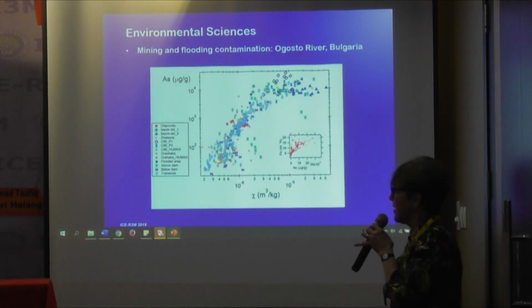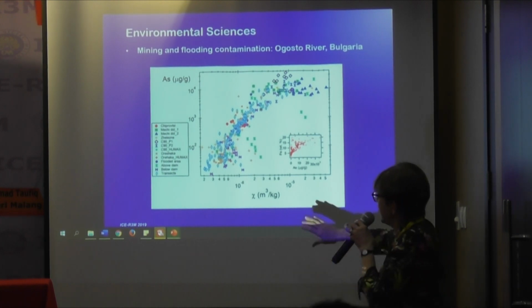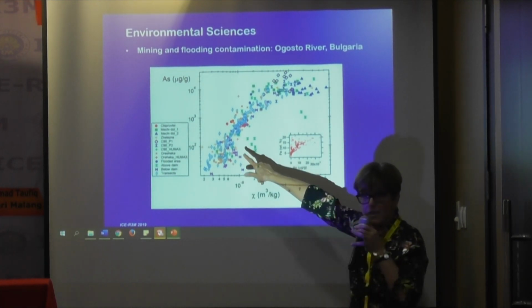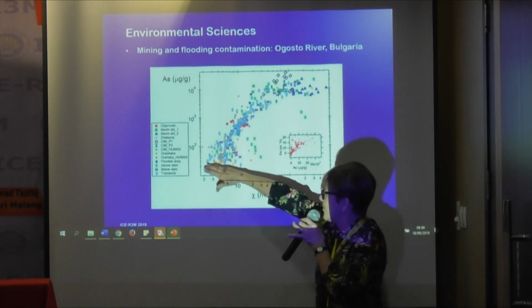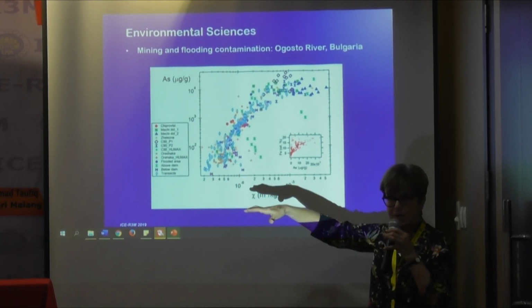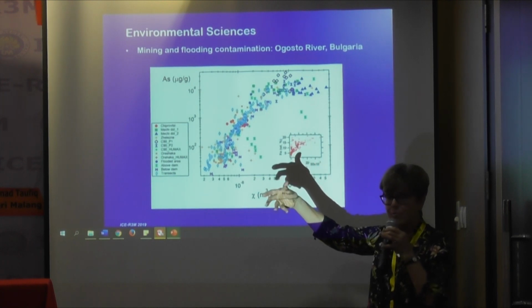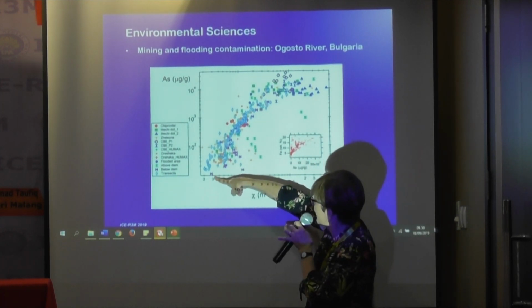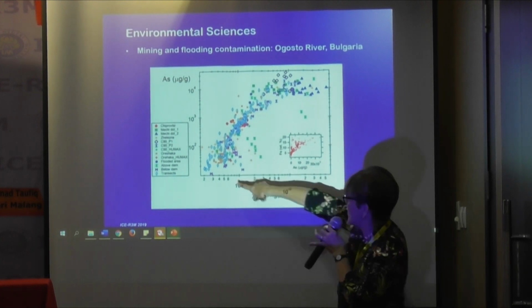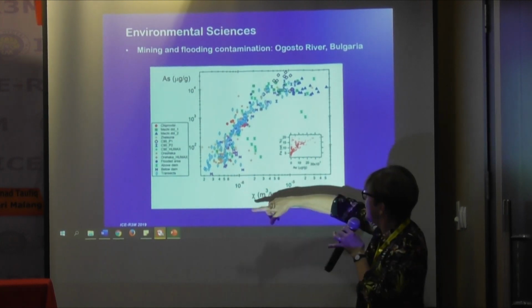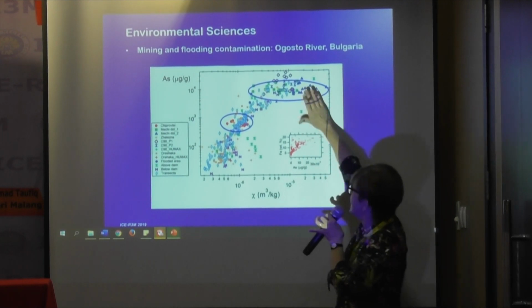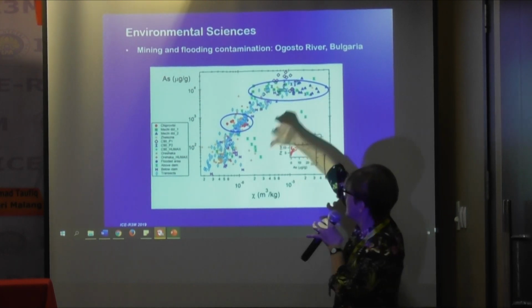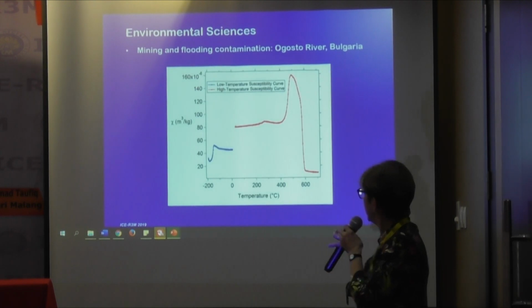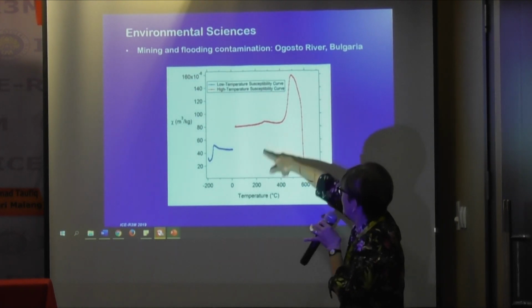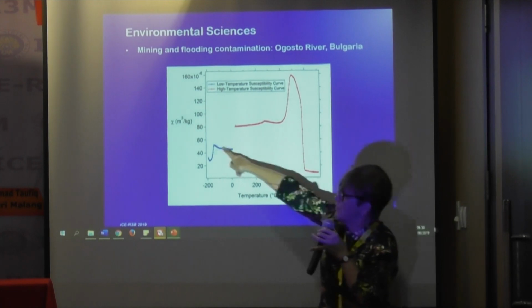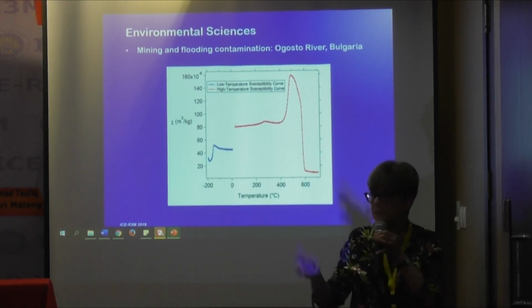Okay, next. Now, more interesting is when we plotted the susceptibility as a function of arsenic, because there's no natural background for the arsenic as there is for the iron, so we think this 4% is just the natural background in the soils. But with the arsenic, we saw arsenic as a function of susceptibility. You have this nice linear relationship. Again, next. You can see the mine here, the tailings here. Okay, next. We found that the material, on the basis of the Curie temperature and the Verwey transition, is magnetite.